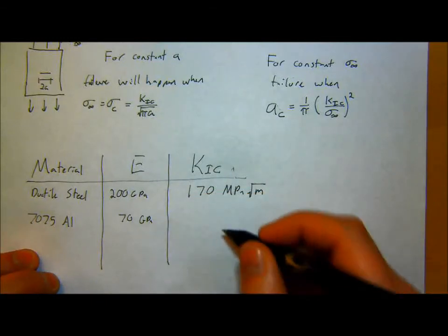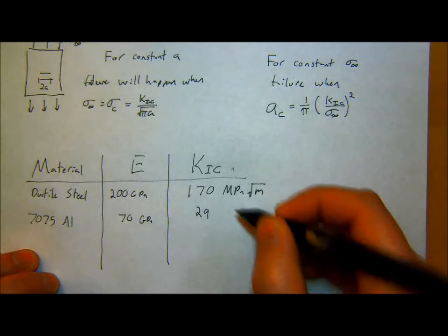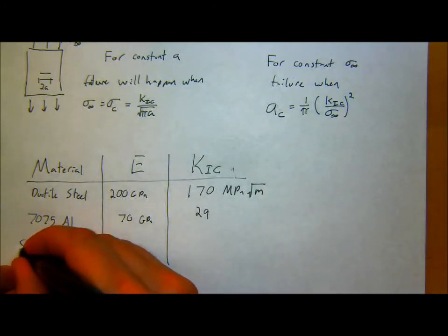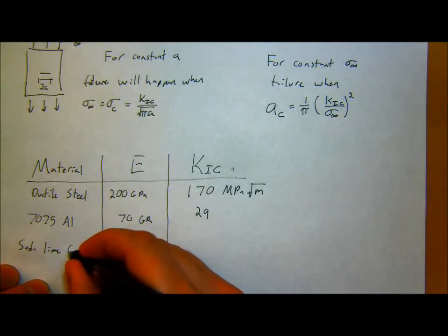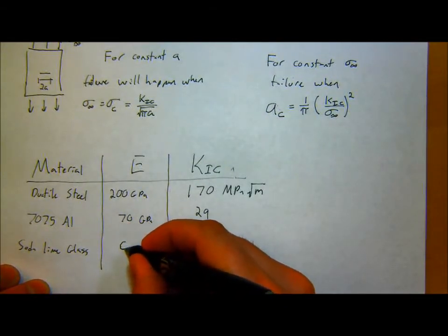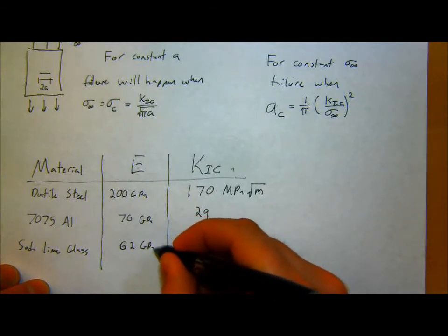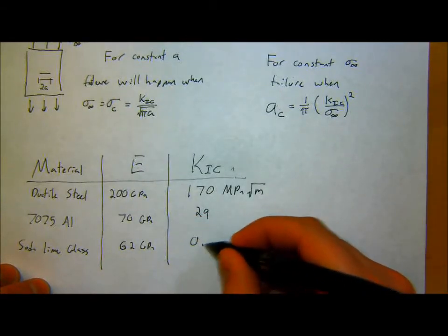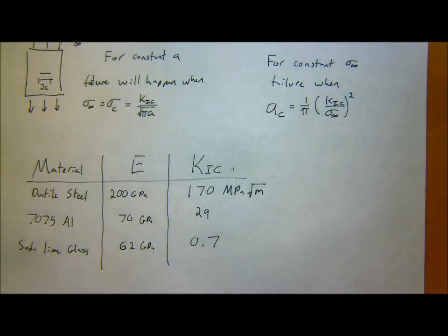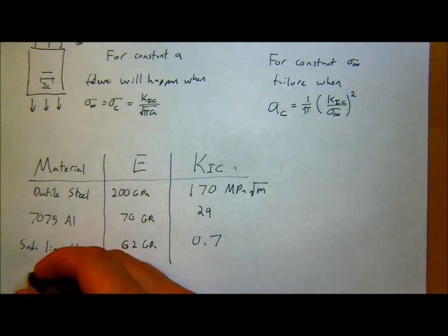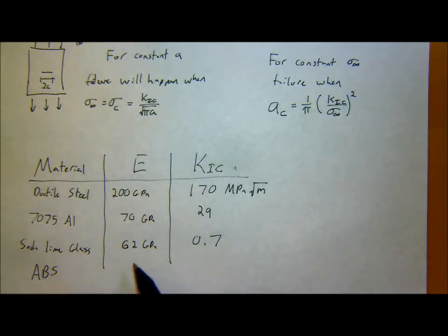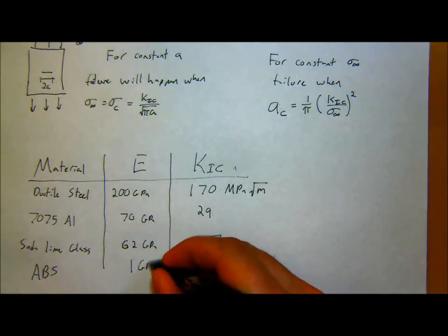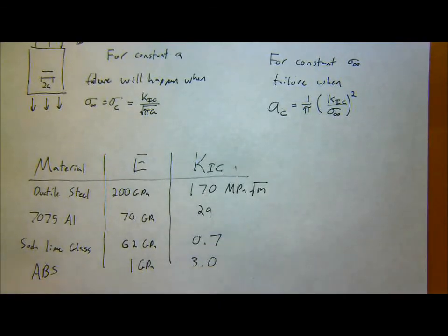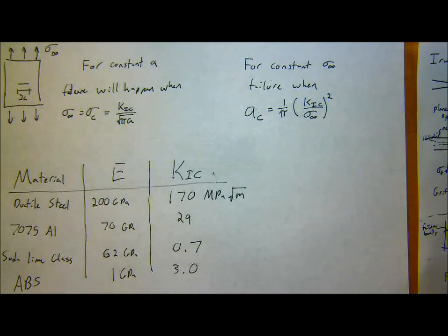Something like soda lime glass would have a stiffness on the order of 62 GPa, and it's very, very brittle. So it has a very low fracture toughness of something like 0.7. And then something like an ABS polymer would have a fairly low stiffness of 1 GPa, but can still have a fairly high fracture toughness. So these two properties act independently. I'll show on Friday an Ashby plot of some of these different material properties and how it all breaks down. But, all right.